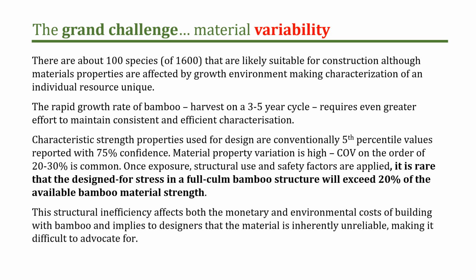And the result of that is that under normal service conditions, it would be rare that the stress in bamboo will exceed about 20% of what's actually available. And so we're not necessarily using the material as efficiently as we might. And this, of course, affects economic and environmental costs of building with bamboo, and might deter designers from selecting bamboo as a material that they view as inherently unreliable, making advocacy a little bit more difficult. And so this is the challenge. And so how do we overcome this challenge?